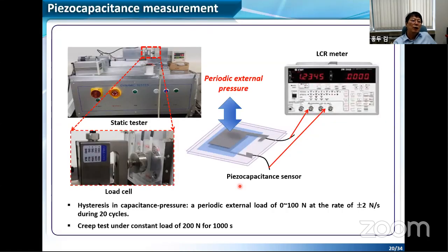To measure the piezocapacitance as well as the piezoelectricity, we made some testers. This is what we call the static tester, to measure piezocapacitance using this direct drive motor, so that we can squeeze and release up to 100 Newton, and we can measure the capacitance using the LCR method.